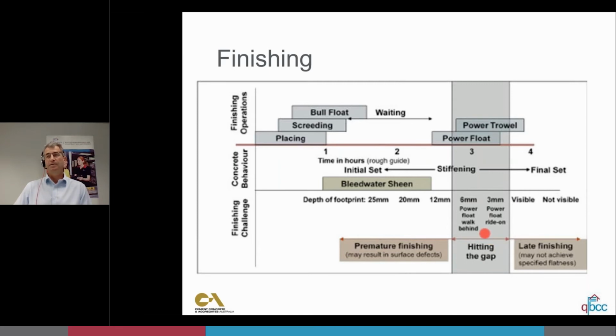And it's really important that we do that surface finishing, because it's that surface densification that provides that surface abrasion resistance. I've seen car parks where on the corners on the ramps, where the steering tires are screwing around on the concrete, that look like exposed aggregate driveways, because all of the paste has been screwed off from the top of that concrete.